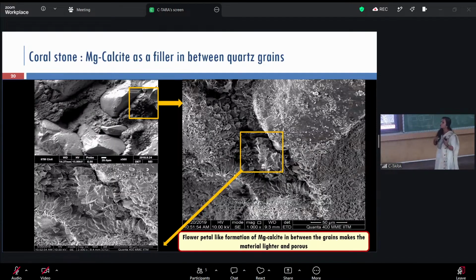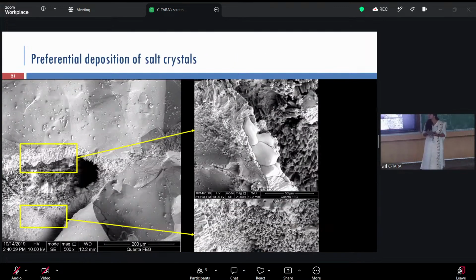Now we wanted to know whether this material will get damaged with salt or not. So we washed the material, dried it, and then we subjected the material to very rough salt weathering cycles. And we saw that after 1 month of cycle, no damage at all. Not even a slight damage was observed in this sample. When we looked at the reason, we saw that there is something called preferential deposition.